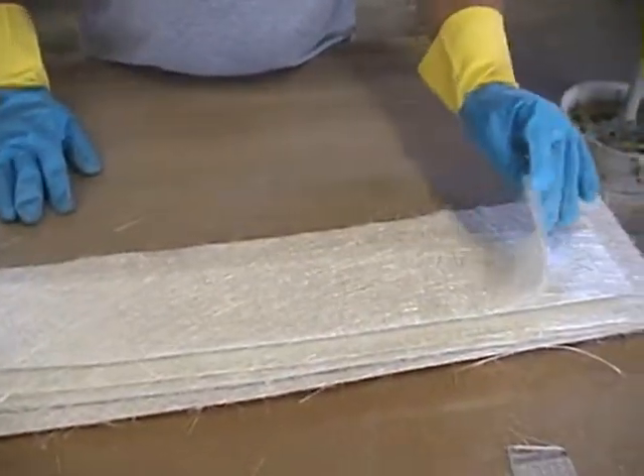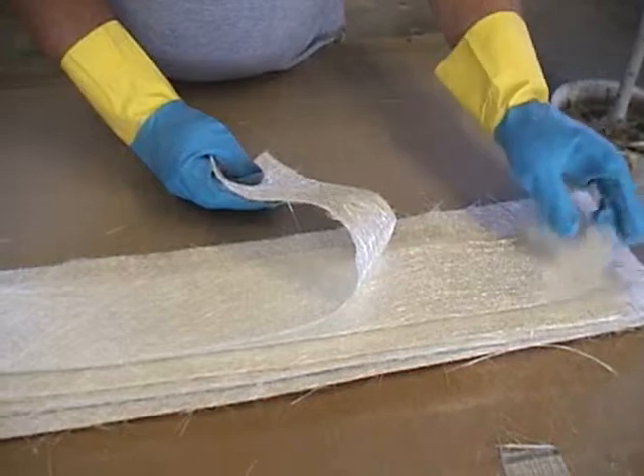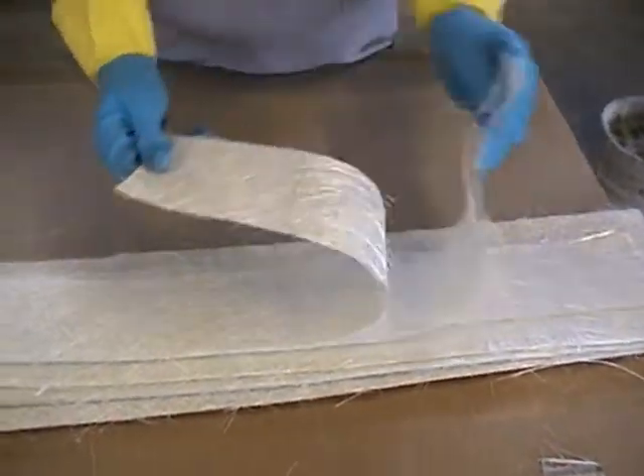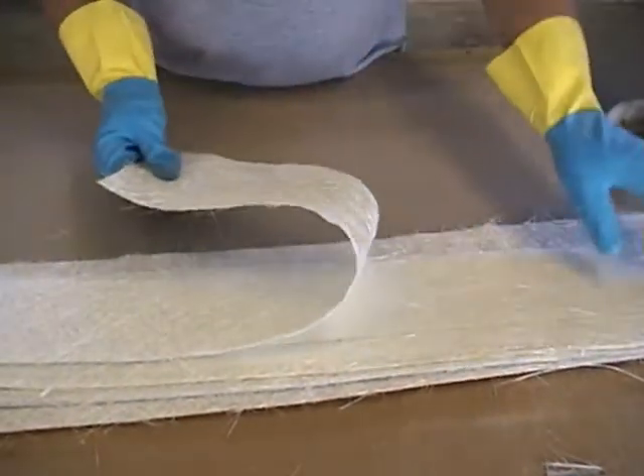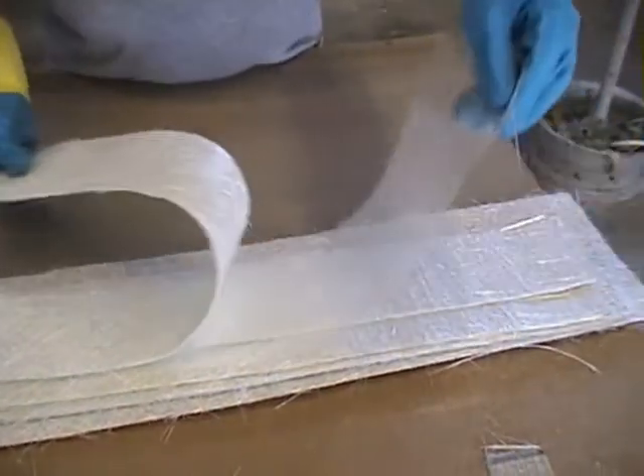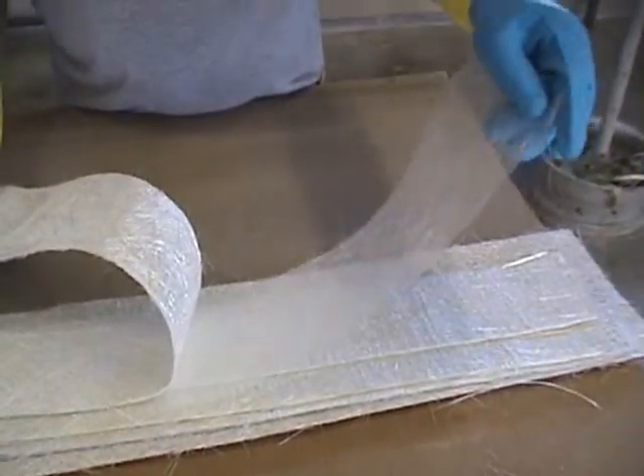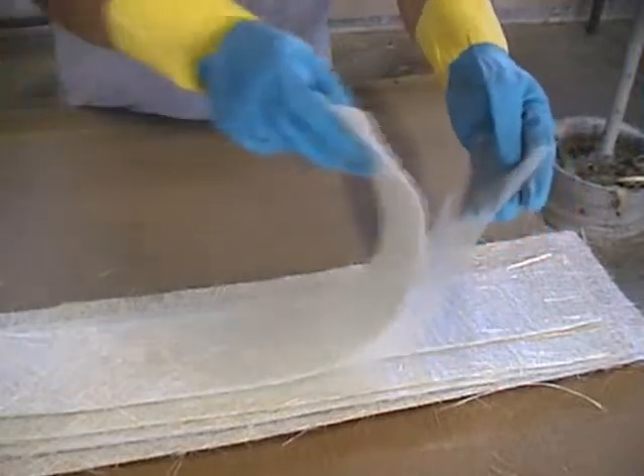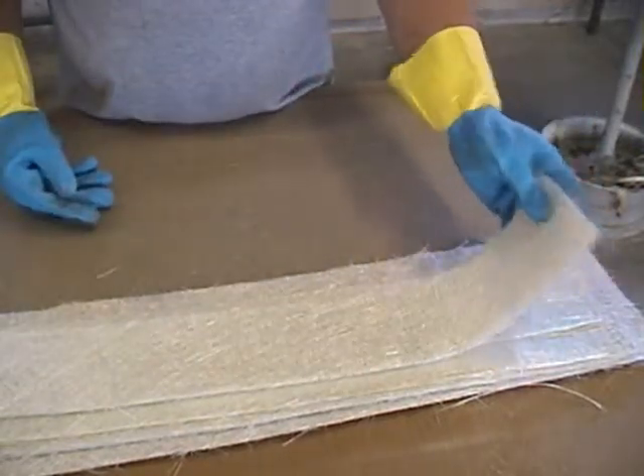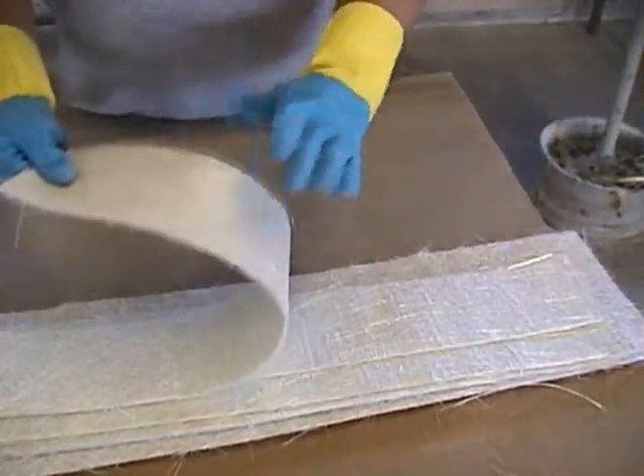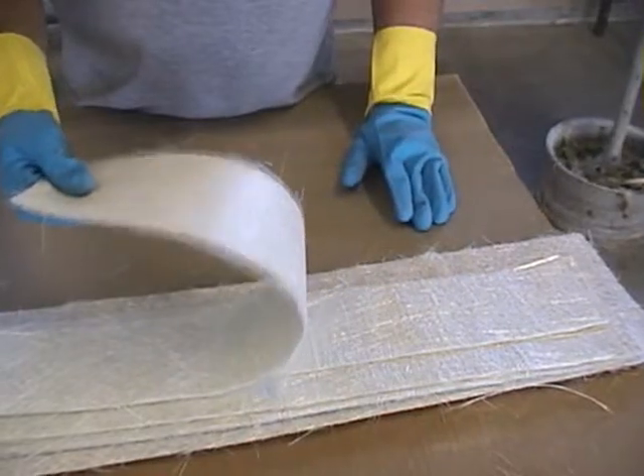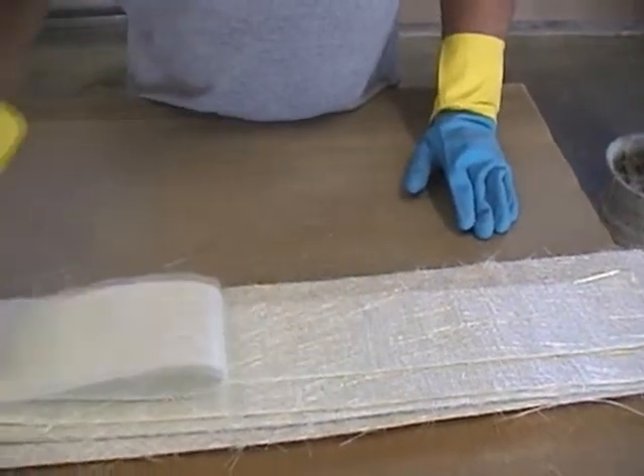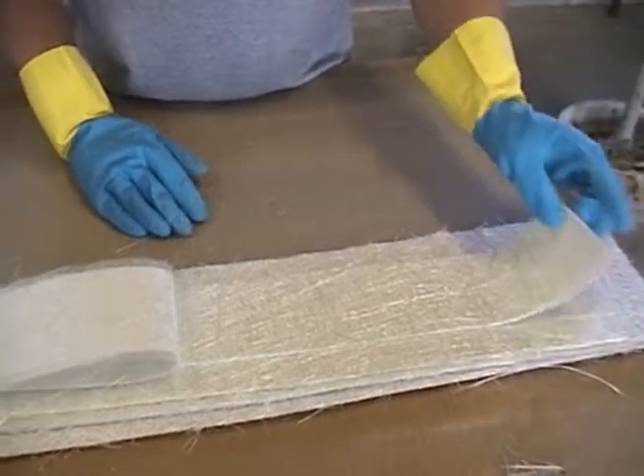The sequence you follow in applying the glass is determined by pressure rating. We will show the glass sequence for an 18-inch butt wrap, 75 psi 6:1. This will consist of 2 layers of chopped strand mat, 1 layer of veil, the veil being the corrosion barrier, and this is your liner. The veil will go against the pipe when we wet this out.